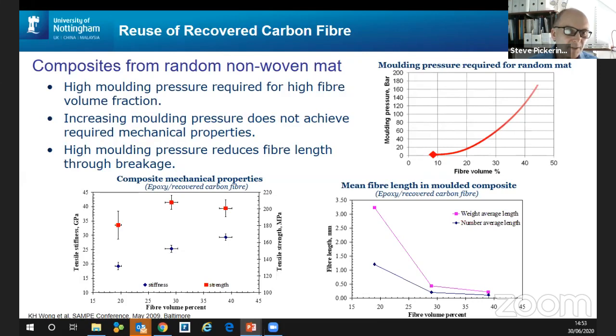So how can you achieve high fiber volume fractions? Well, you can't do it with random fiber orientations, and we've done some work with making random non-woven mats using a paper making technique to make some composites. And this graph here shows the mechanical properties, the stiffness and the strength on the y-axis, and different fiber volume fractions on the x-axis. As we increase the molding pressure to squash the fibers together and give high fiber volume fraction, the best properties were achieved at around 30% fiber volume fraction.